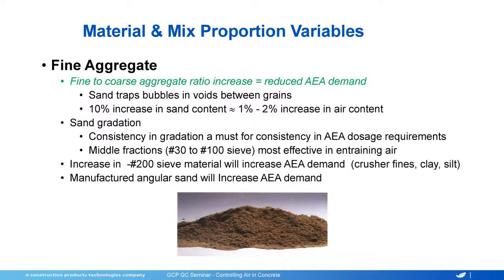So again, the 30, the 50, the 100, and I would tell you especially the 50 and 100 sieve, that's where you need consistent material to be able to produce consistent air. The amount of sand in the mix is also going to impact that, and we'll talk about that in a bit. Again, that material passing the 200 sieve may not be clay or silt, but tracking that, doing a sand equivalent or some other test that shows you what that material is, is key to track any changes with that.